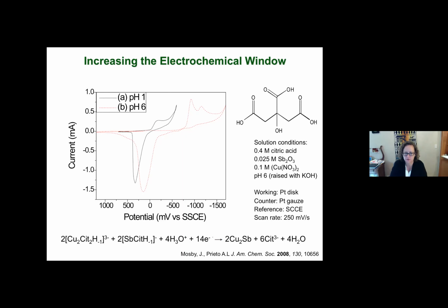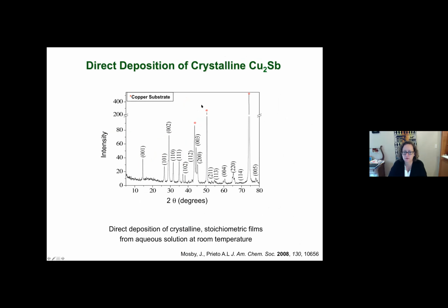If you use citric acid though, and you raise the pH, you dramatically extend the electrochemical window. Here you can see two reduction events that correspond to the deposition of copper and antimony. Copper is a really anomalously fast diffuser, and so you nucleate and grow copper antimonide. And the citric acid helps to adsorb onto the electrode surface, so you don't evolve hydrogen until very negative potentials. The as-deposited copper antimonide is crystalline at room temperature, and this is quite important because we need the electrochemical performance of copper antimonide, not the mixture of copper and antimony.